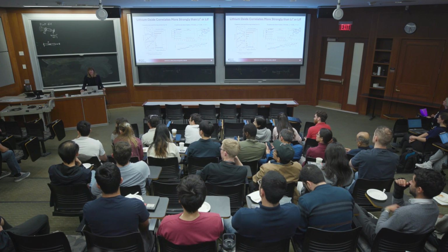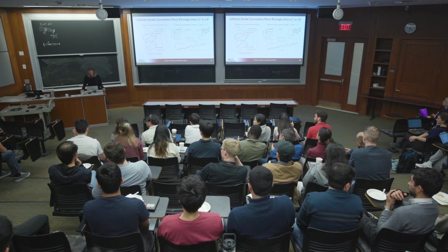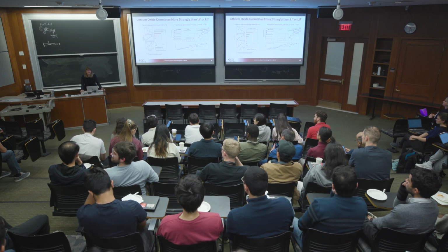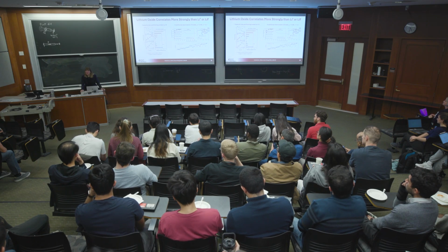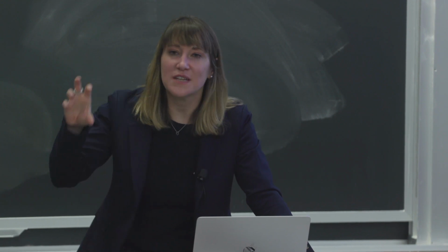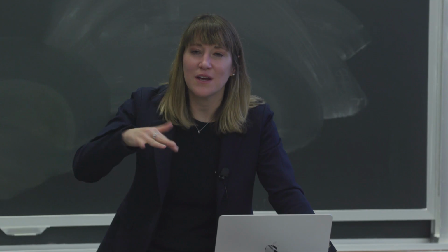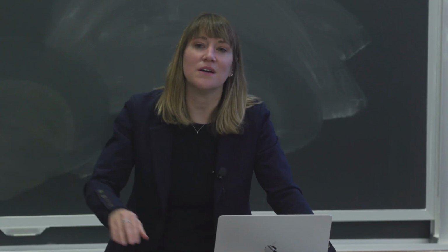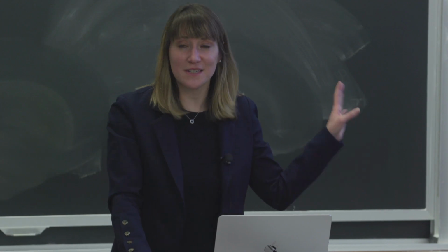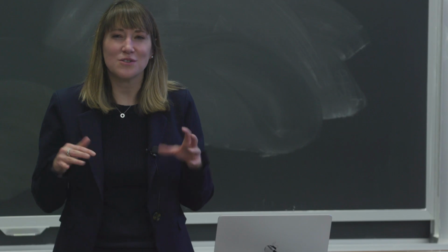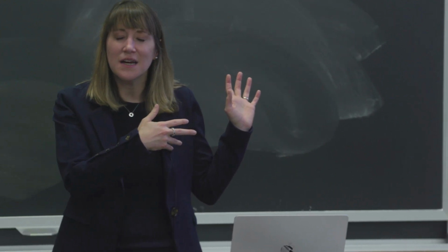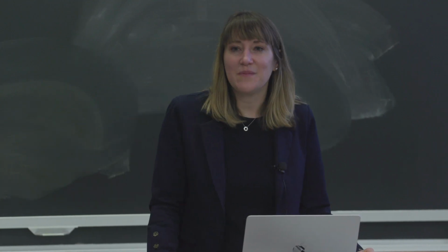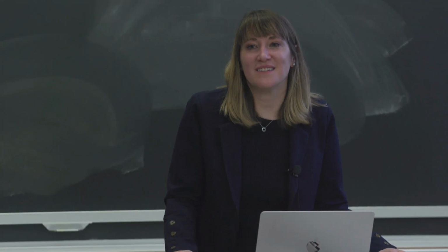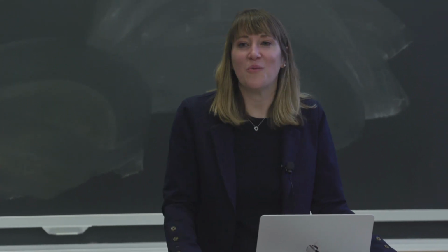Granted. But if you do that at different currents, you change the dynamics, right? You ask for more or less. Is there some sort of dynamic study that could hint at that? Absolutely. I would say the state of some modeling has largely overlooked the presence of an SEI. Looking at kinetic and dynamic phenomena of plating lithium, you can look at what's happening locally in terms of concentration gradients in the bulk electrolyte, perturb that, and see how the resulting deposition responds. That's more akin to a classical electroplating type system, absent an SEI. It's a lot harder to get that right with the SEI present because there are so many parameters you would have to put into your model to capture it. I don't want to say it's not been done, but that's a great question and it should be done. It's still an open area to figure out exactly why these things collapse the way they do.